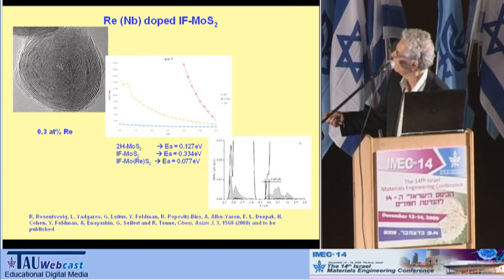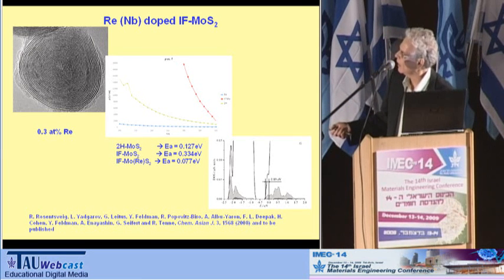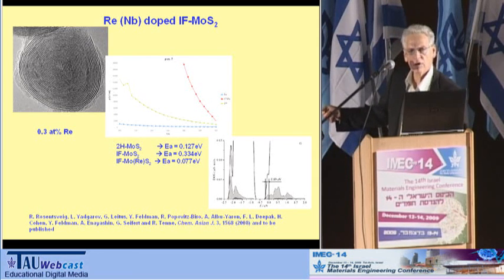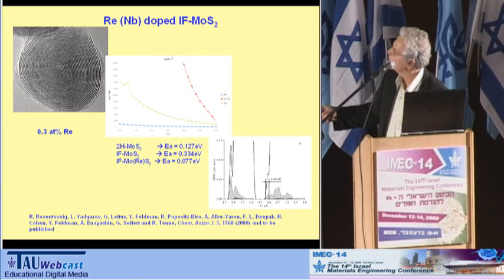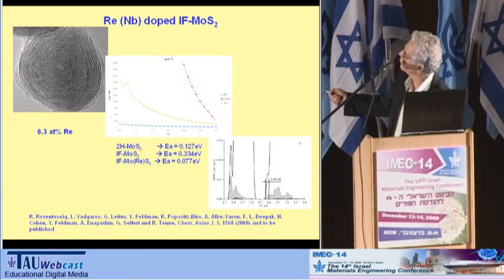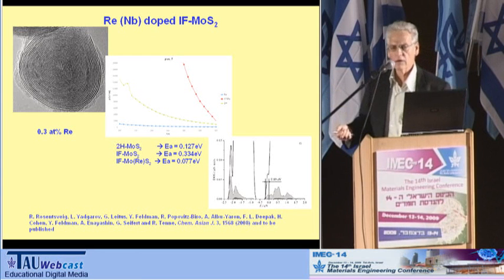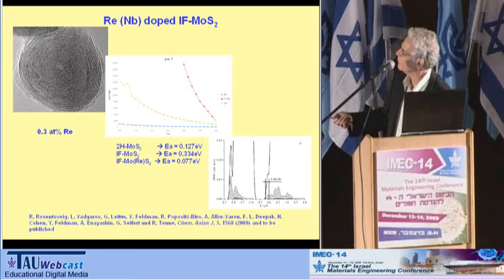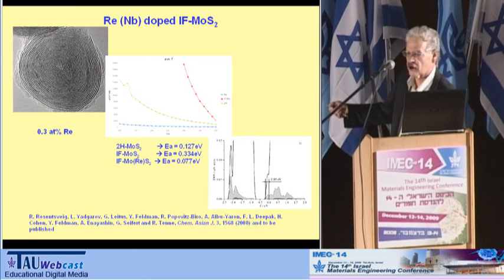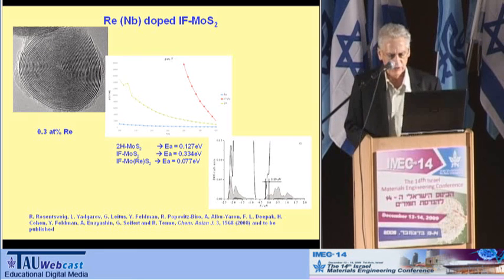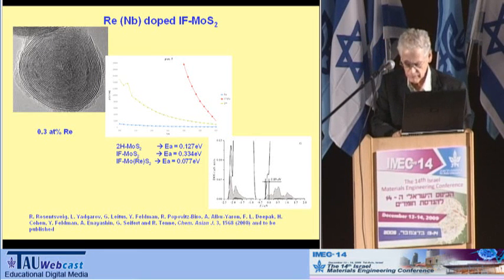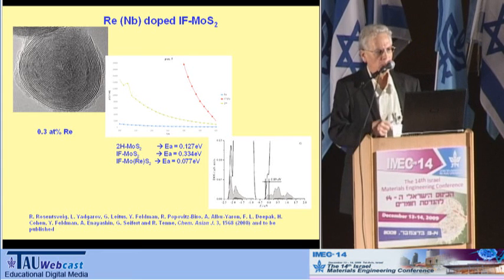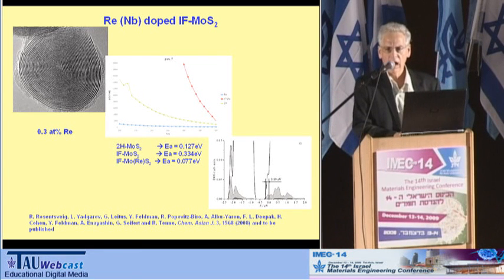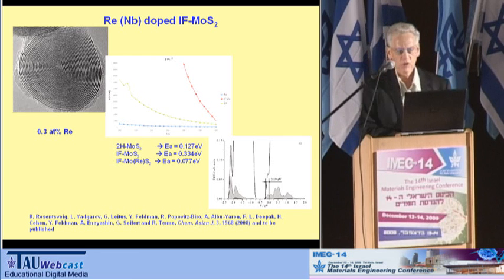The calculations were done by Professor Seifert and Andrei Enyashin in Dresden, in the Technical University in Dresden, and they calculate the rhenium doping of molybdenum disulfide nanotubes, and you see that the donor level, which is here, is only a few hundred millivolts from the conduction band, and that's more or less the same activation energy that we found for the donor level in the rhenium-doped molybdenum disulfide nanoparticles. We can also dope nanotubes using a similar strategy, and we can get highly conductive nanotubes. Once you have this, you can do a lot of other things that we weren't able to do so far.